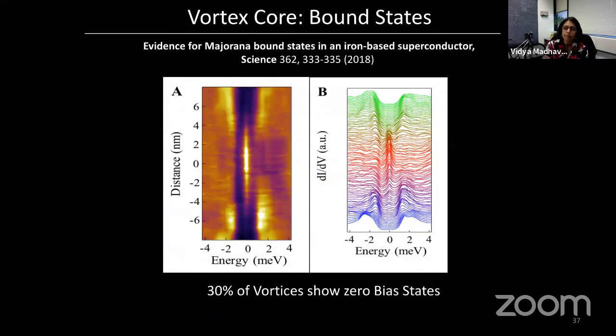In fact, this peak in the density of states was discovered not by us, but by another group from China, Hong Ding and his collaborators, in 2018. And what they found, which was really interesting, is that not all of these vortices show 0 bias states. In fact, only 30% of the vortices show 0 bias states. So this was a huge mystery at that time. Why don't all the vortices show these Majorana bound states?